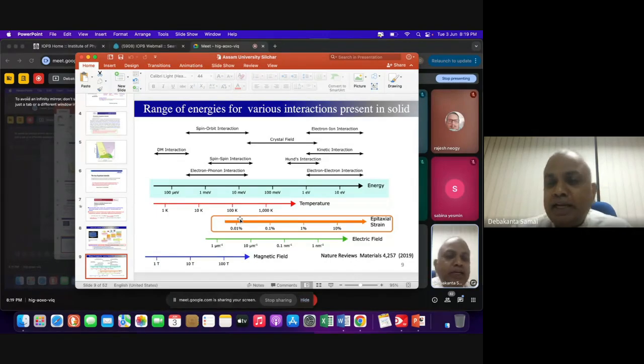You look at the spin-spin interaction. We talked about Heisenberg's interaction. On this scale, the spin-spin interaction is roughly 1 milli-electron volt to 10 or 15 milli-electron volt. That is the order of 100 K. But even by straining your material this way, putting one layer on top of another layer, your energy scale is equivalent to that. So the property of a material depends upon the subtle competition, the interplay between various kinds of energies present in the system. Which energy wins determines the ground state.